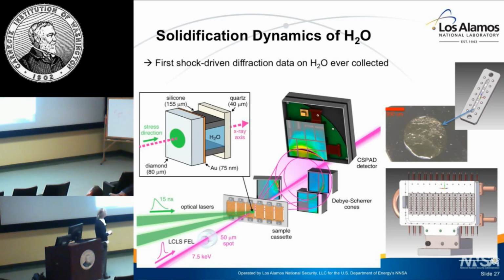You can see in this little cutout, there's a meniscus of the water sample. This is shiny to your eyeball because there's a gold layer. So the gold layer will give diffraction, powder diffraction signal. I can use it as an internal pressure calibrant, okay? And that, we'll see that's advantageous. So the setup is shown here. Again, our sample stage is in the center of this image.